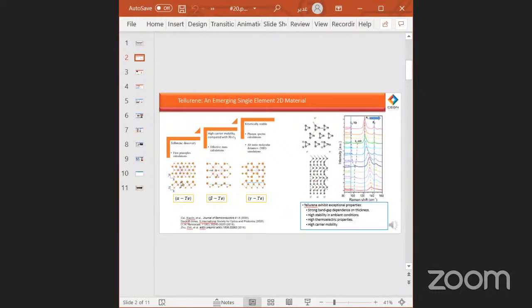When we were working with 2D black phosphorus and graphene, we faced major problems regarding the preparation of devices. For example, in graphene photodetectors, the zero band gap makes it a conductor all the time, damaging the device sensitivity. On the other hand, black phosphorus has a small band gap, however, which makes it highly reactive at ambient conditions and also limits its application. Therefore, recently, tellurium has attracted more interest because it is exceptionally stable at room temperature and has low toxicity. Also, it has a higher carrier mobility compared to MoS2.